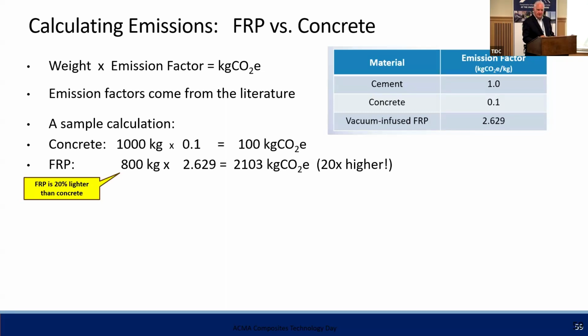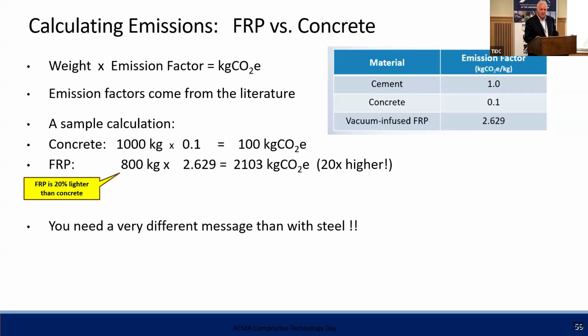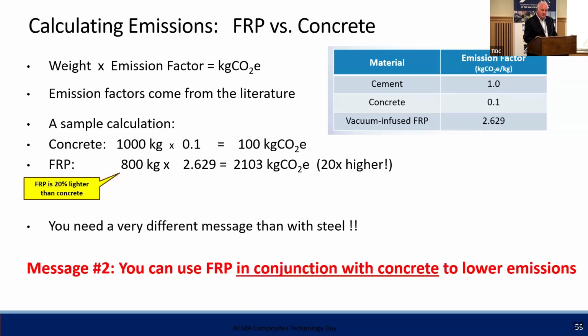Now, let's do it for FRP. FRP is lighter than concrete, about 20% lighter, so I've only got 800 kilograms there. But then I have to multiply it by 2.629 and I get 2,100 kilograms of CO2 equivalents. That's 20 times higher than concrete. So replacing concrete with FRP does not reduce emissions. You need a very different message than with steel. And message number 2 is that you can use FRP in conjunction with concrete to lower emissions.